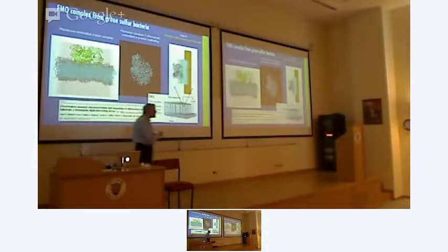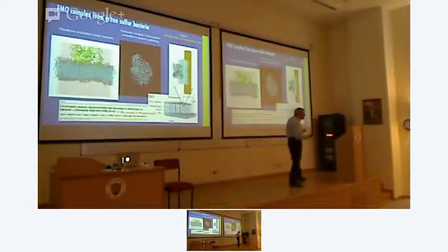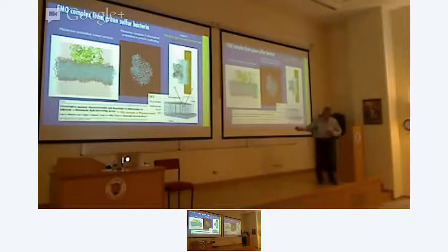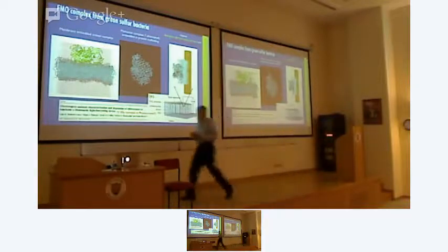The chlorosomes are the harvesting, they're natural. So this is a biocomposite, a bio-artificial composite. And in this particular case, you could increase the photocurrent of this device, using the fact that I'm now taking all my photons and transferring them to excitation of electrons and holes in this thing. You can increase the photocurrent by a factor of 30 by doing something like this. So it's a huge potential.